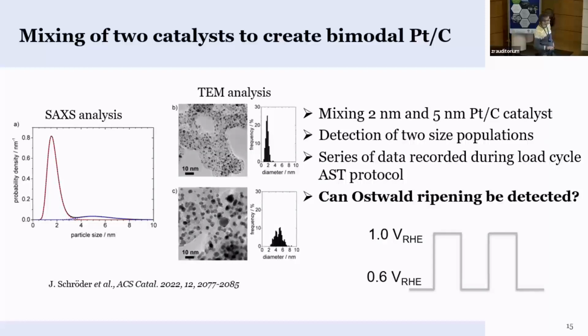What we did is we just took these two well-defined commercial catalysts and mixed them. They are just powders, so you can mix them. But of course, the particles then are on separate carbon supports. So one carbon has only small and one has only large particles. And if you do small angle X-ray scattering, you can easily distinguish the two populations.